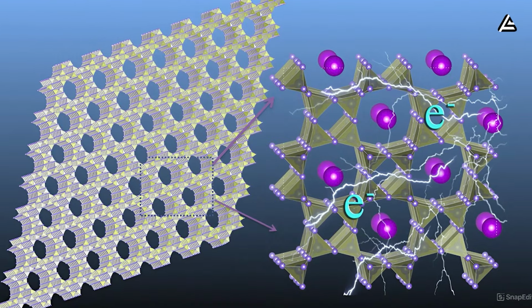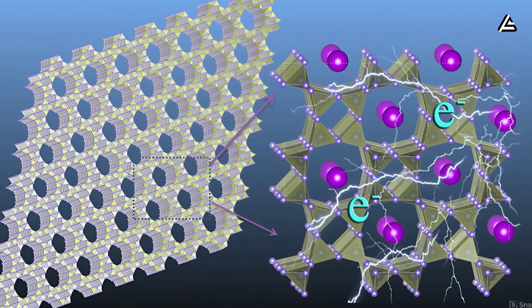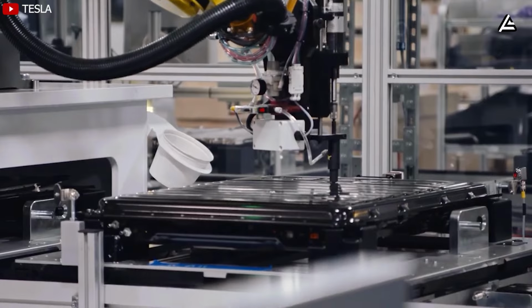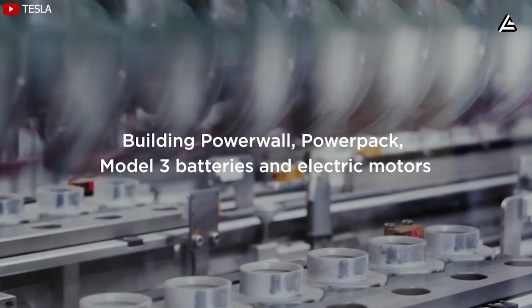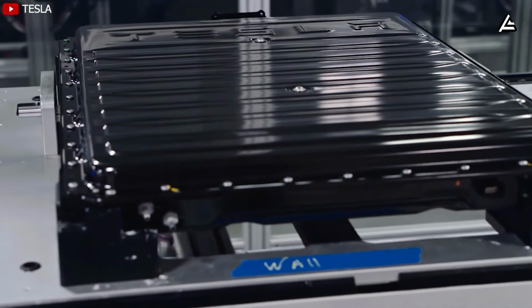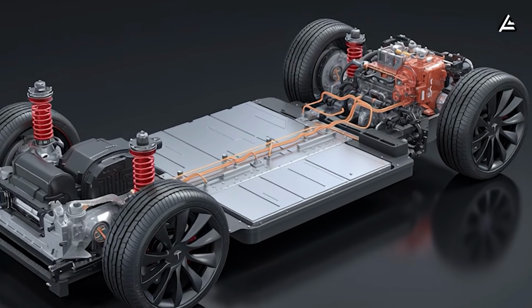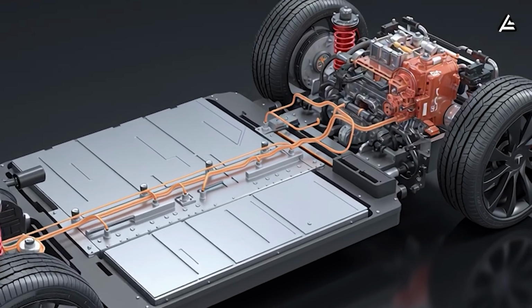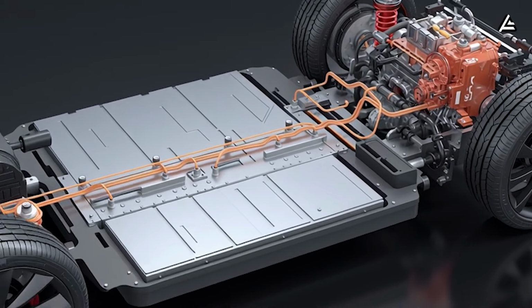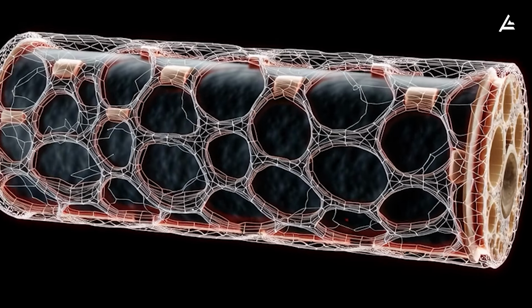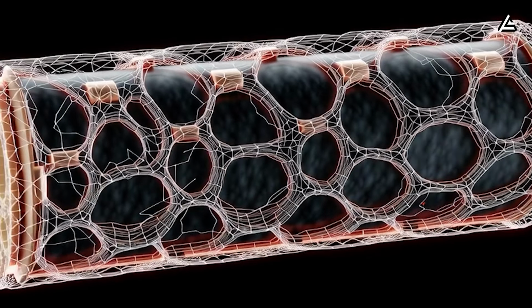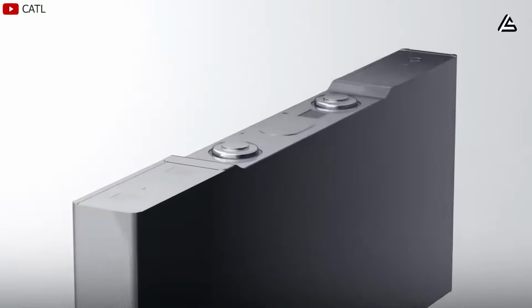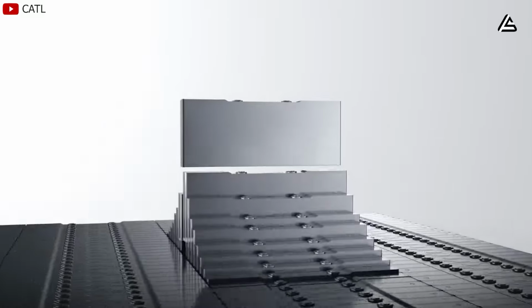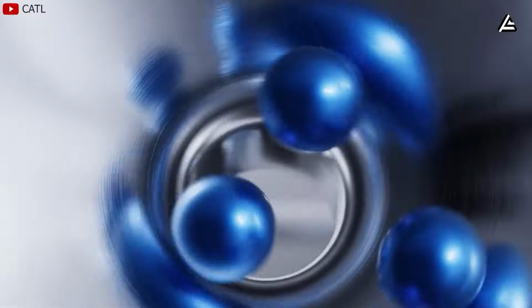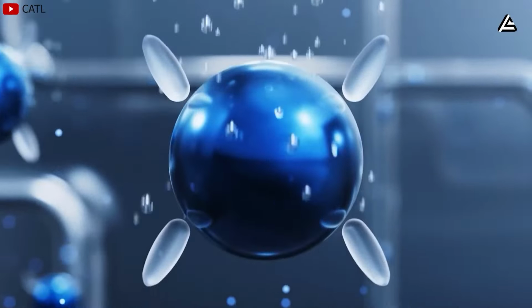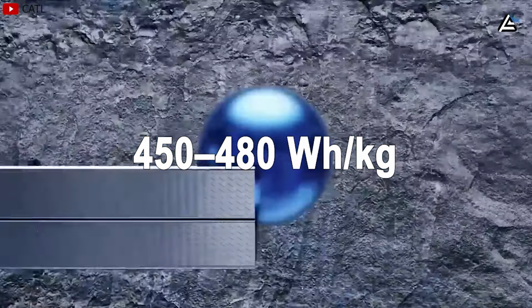The newer and smarter approach they're working on now is something called 3D porous electrode architecture. Instead of adding new materials, Tesla redesigned the entire internal structure of the battery cell to make better use of ion storage space. In older aluminum prototypes, the flat anode and cathode surfaces only stored about 60% of the available aluminum ions. This time, Tesla built a nano-porous electrode network, packed with millions of holes just 5 nanometers wide. This design increased ion storage efficiency from 60% to 95%. Energy density rose from 200 watt-hours per kilogram to around 450 to 480 watt-hours per kilogram.